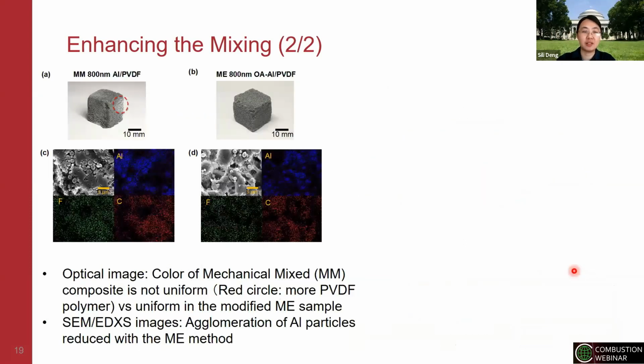And to skip some of the details and directly bring you to the conclusions, this is an optical image of a mechanical mix, so just directly dispersing aluminum in the PVDF polymer. You can see the color is uneven, meaning that there's a lot of polymer separated from the aluminum. After this is the same material but using the micro-emulsion technique, and we can see the color is more uniform. And from the detailed SEM and EDX images, we can see that the particles are embedded in the polymer matrix more evenly and more uniformly.